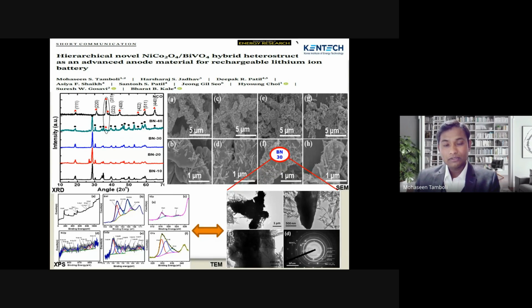The 30% BiVO4 NiCo2O4 sample we have analyzed by transmission electron microscopy. In that sample, we can also observe the same results, consistent with the FESEM. You can see here the nanowires of NiCo2O4 connected with the dendrite-like BiVO4. After that, we studied the XPS. In the XPS survey spectrum, it shows that all elements of NiCo2O4 and BiVO4 are present, such as nickel, cobalt, oxygen, bismuth, and vanadium. All the elements are present here.